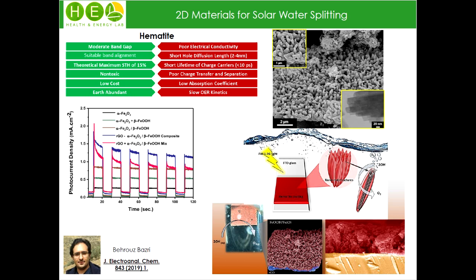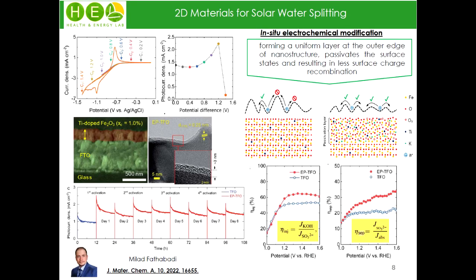The electrons can jump easily from the hematite to the RGO, and then to the back contact, and then to the external circuit. So we can enhance charge separation in the system, and finally gain a photocurrent density nearly 3 times that of the pristine hematite.